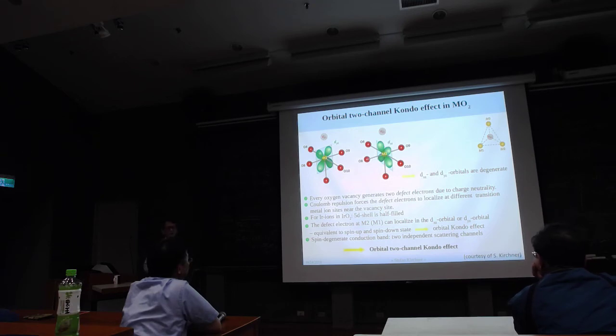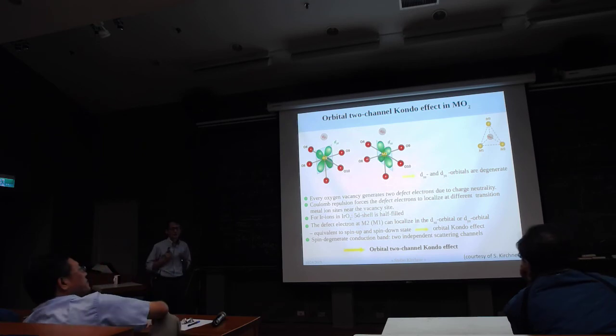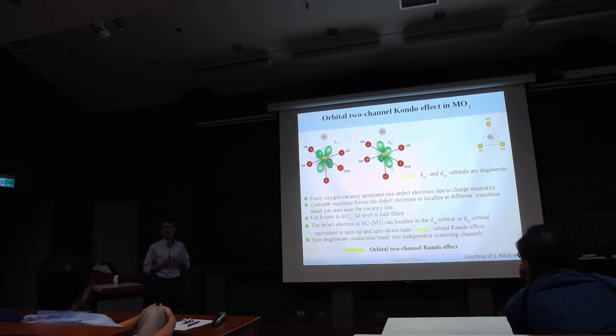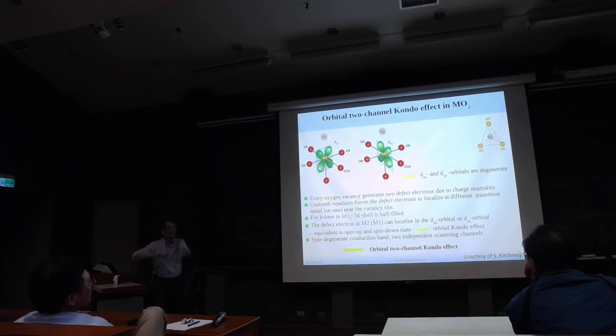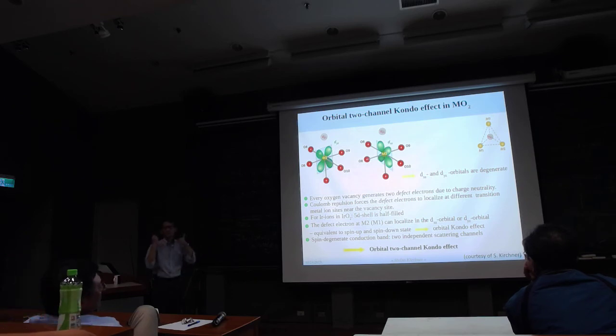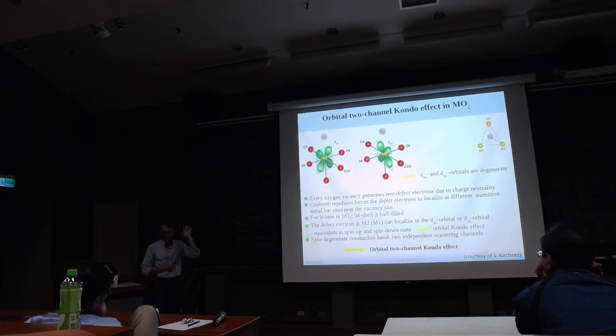But what is interesting is that in this iridium dioxide, there is no spin involved. We are not talking anything about spin. In our conduction Fermi sea, one half of the electrons are spin up, the other half spin down. These two we can consider as two independent and equivalent Fermi seas, both of which try to screen or interact with this defect. So we have two channels, spin up conduction electrons and spin down conduction electrons. They are equivalent but independent. And we have one defect.